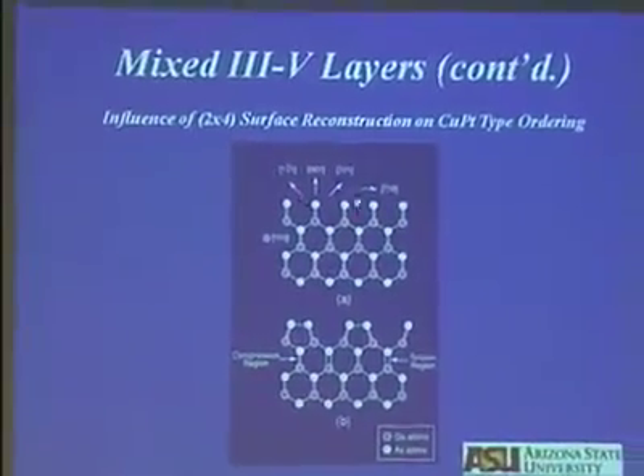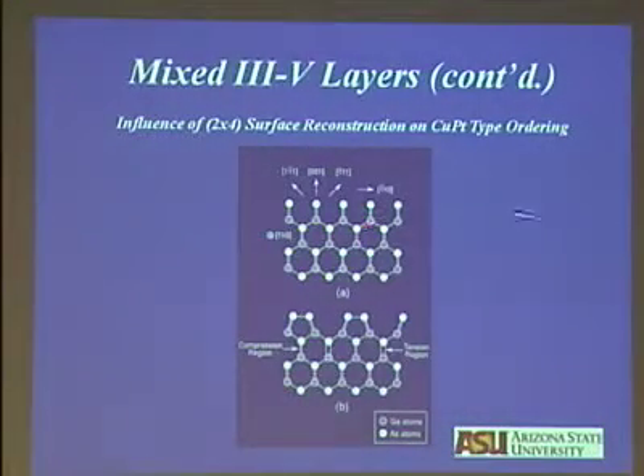Now, how does the ordering occur? Mechanistically, the same argument, the size difference, helps you to understand that one. This is a cross-section along the 110 plane, and you have seen this earlier. Now, when you have exposed arsenic atoms on the surface, group 5 atoms, as I said, there are a lot of dangling bonds on the surface. So to lower the electronic energy of the system, you form dimers, as shown here. And we have done valence force field calculations to illustrate. Underneath the dimers, the arsenic bonds to arsenic to form a double bond, and there is a compressive stress region. In between the dimers, you have a tension region.